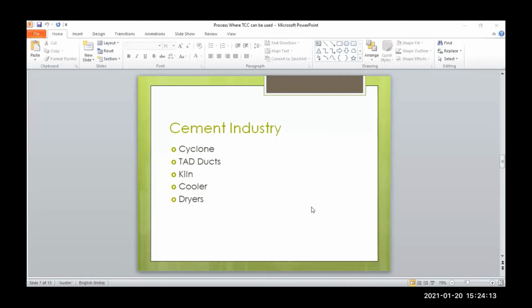Then the cement industry. The cement industry is the biggest consumer of thermal energy. We can improve the heating efficiency by applying that coating on the cyclone external surface, where the internal temperature is around 800 degrees centigrade and the external shell temperature goes around 120 degrees centigrade. We can reduce that temperature by simply applying that external coating, and around 30 to 35% temperature drop can be achieved on the external shell of the cyclone. Then there are TAD ducts where the shell temperature goes around 120 to 150 degrees centigrade. That can be applied with this coating.